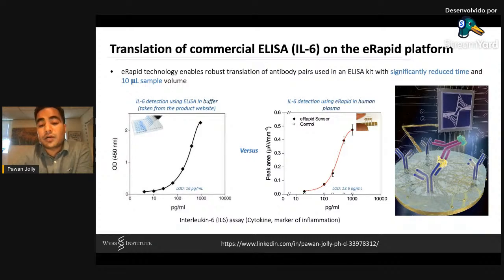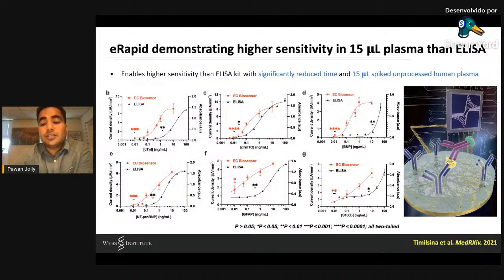This was really exciting for us, that we were able to match the limit of detection without doing any sample preparation. Of course, in this case, it was plasma. For this case, we used interleukin-6, which is a cytokine, a marker of inflammation. Following that, we did a range of biomarkers. Here is a comparison between our electrochemical sensor versus ELISA, and you can see the magnitude of sensitivity difference between both when used in human plasma. With our sensors, we were able to perform in nearly 30 minutes, while the ELISA took a couple of hours and more sample volume. This really shows how we can push the sensitivity using our electrochemical sensors.